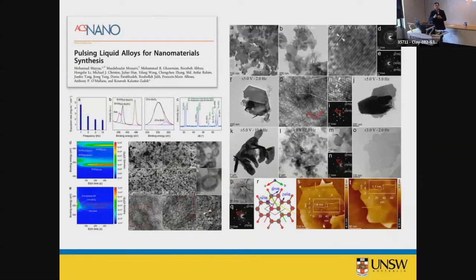So for instance, zinc comes as a zinc core with zinc oxide coverage around it, these hexagonal shapes of zinc. And we can get really good quality large-area zinc oxide or zinc out, depending on, for instance, how you change the pH of the environment. Very interestingly, tin comes as a tin metal core and some tin oxide around it, but they come as round particles. So we can use the templating effect for some of the metals, not for others, depending on changing the condition.